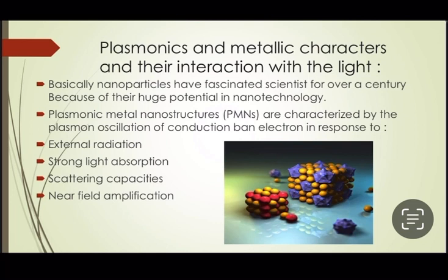Plasmonic nanoparticle lattices exhibit strongly enhanced optical fields within the subwavelength vicinity of the nanoparticles, two orders of magnitude higher than those of the individual unit. These intense electromagnetic fields can manipulate nanoscale processes such as photocatalysis, optical spectroscopy, non-linear optics, and light harvesting. Plasmonic nanostructures are characterized by the plasmon oscillations of the conduction band electrons in response to external radiation, strong light absorption, scattering capacities, and near-field amplification.